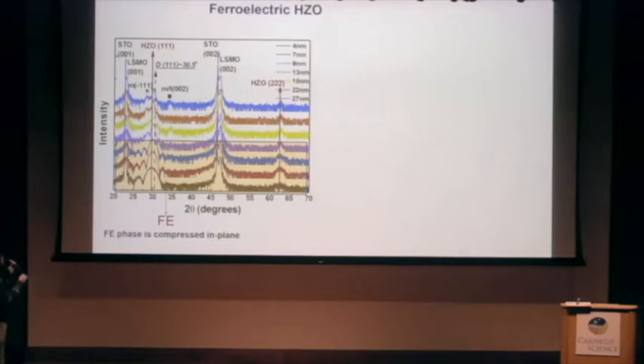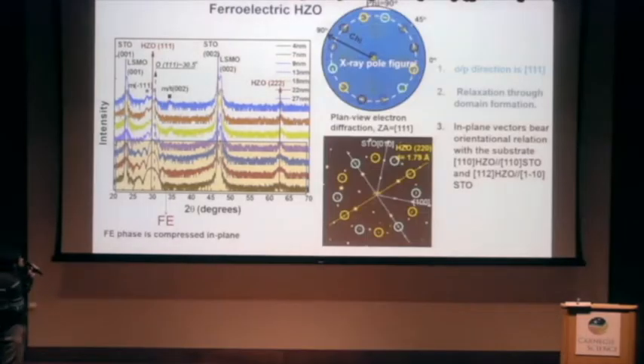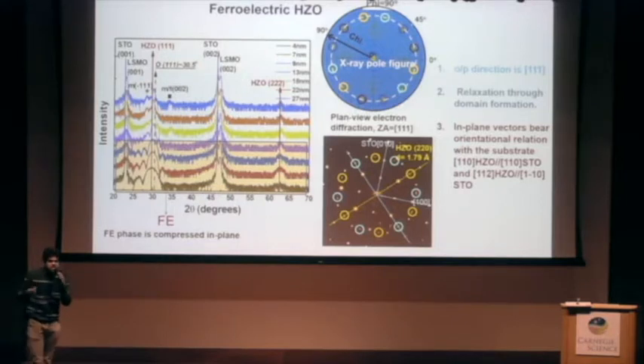There is a lattice parameter which is larger than what is reported in literature, and also larger than in the thicker films. So our ferroelectric films seem to have a longer out-of-plane parameter, which could be coming because of compression in plane. Okay, so you can do some pole figure analysis around this 111 peak, and then see that this corresponds to a domain structure of 4 different domains, which are rotated 90 degrees with respect to each other.